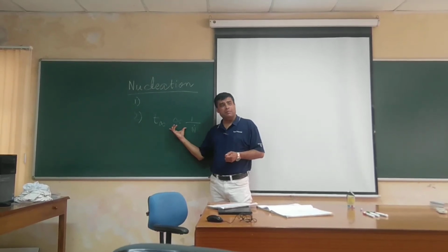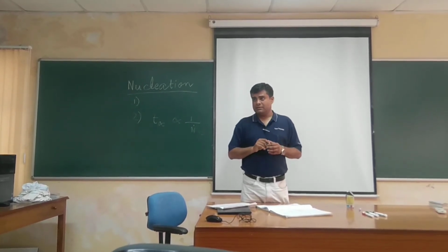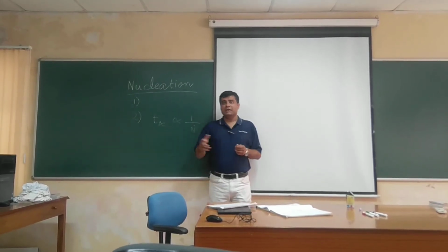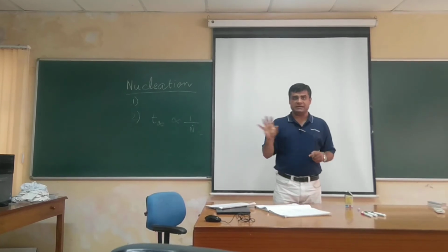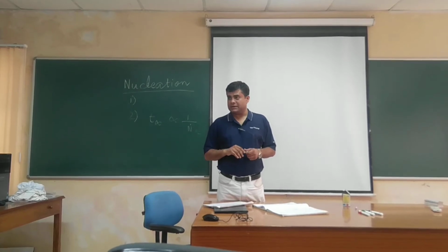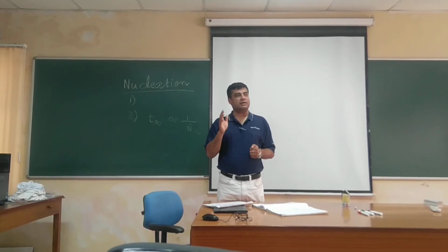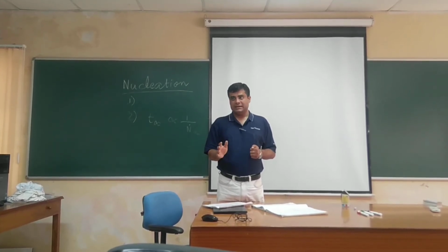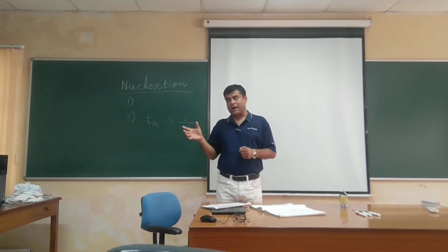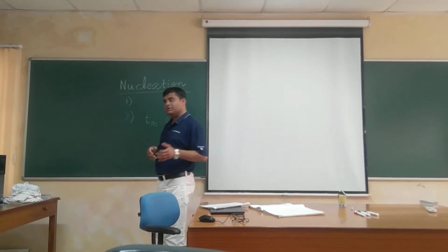This statement is valid only when the growth rate is not coming into the picture. Because the time required for a fixed fraction transformed involves both growth and nucleation. So in diffusion-less transformation, where the growth rate is very rapid and not a function of temperature, we can take this assumption that time required is inversely proportional to nucleation rate, or the overall transformation rate is just the nucleation rate.